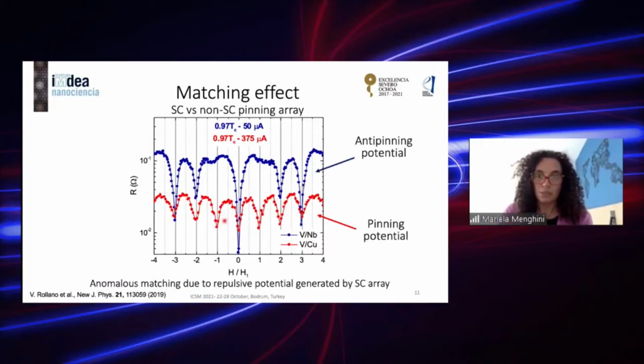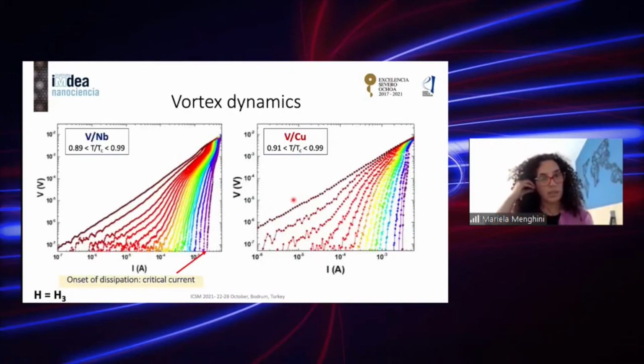This is more clear now when we compare these magnetoresistance curves for similar temperatures, when the pinning potential or nanostructured array is made of normal metal. This is the case of the red curve, the vanadium copper hybrid structure, where you can see clearly the minimum at the first matching field and the second and third, and that the intensity of these minima is much more similar between the different fields, while this is not the case for the superconducting nanostructure.